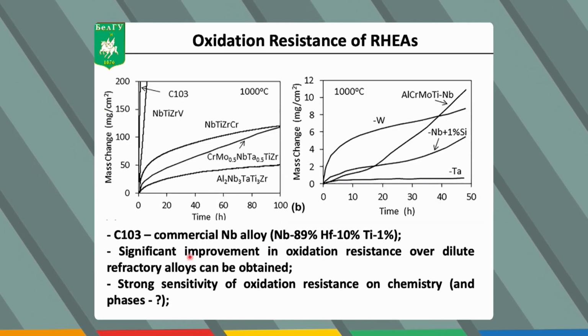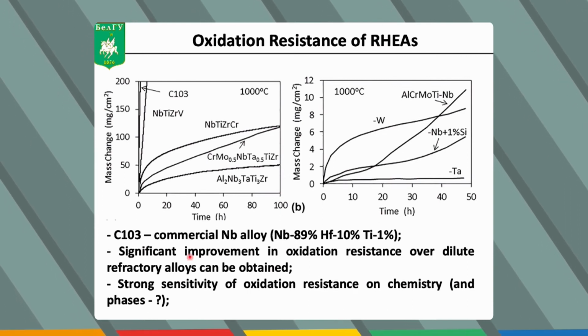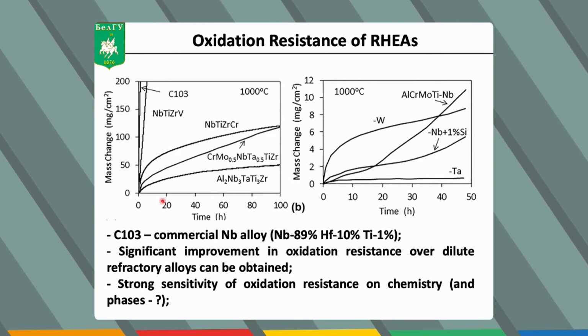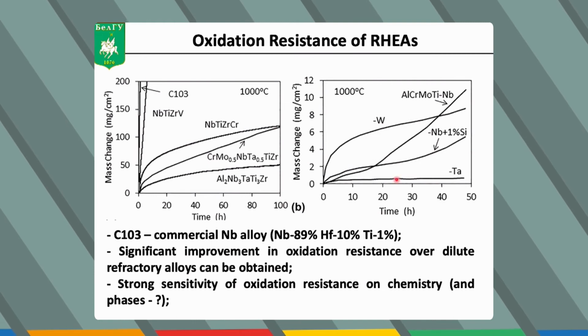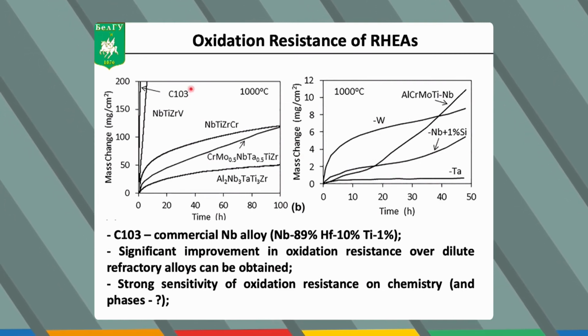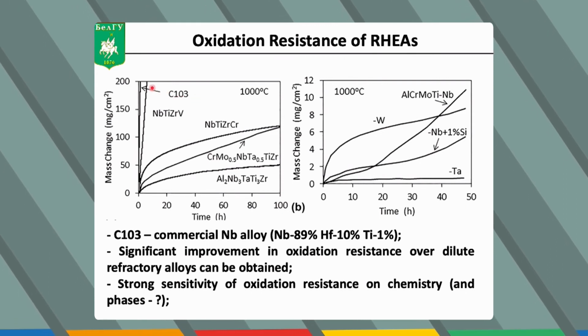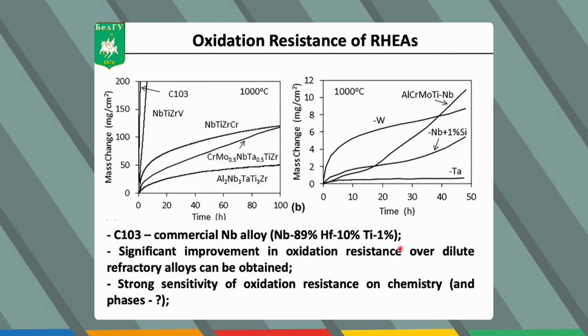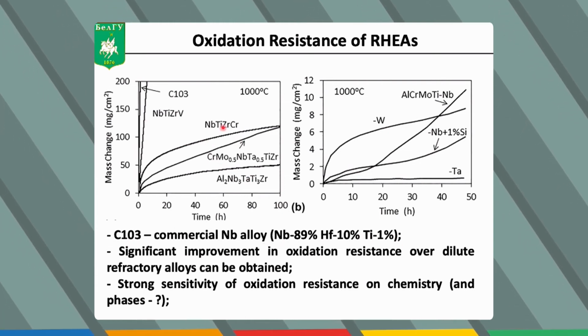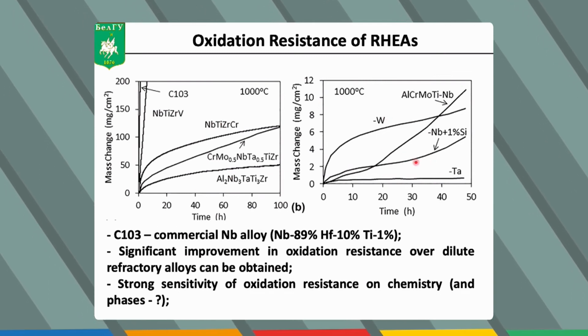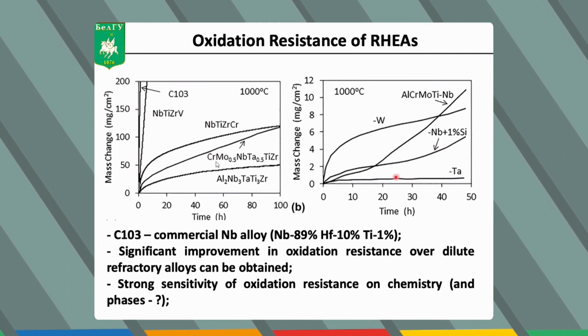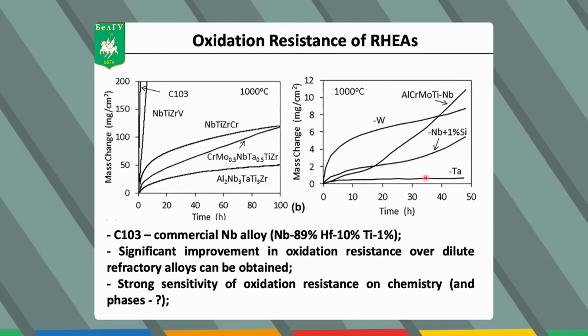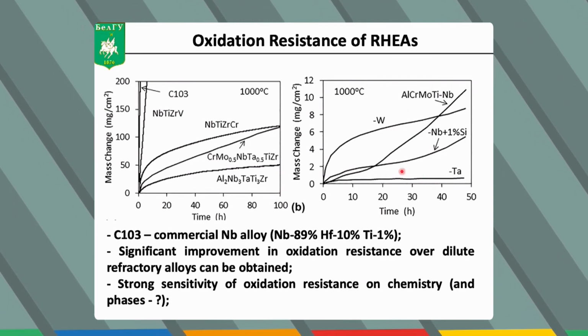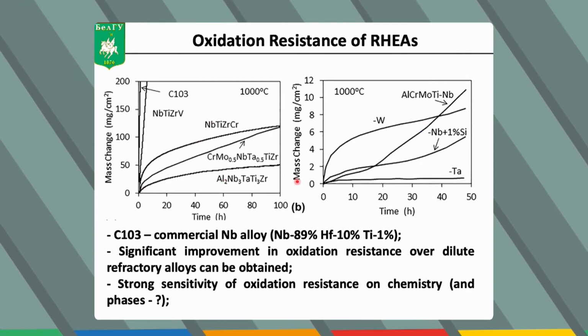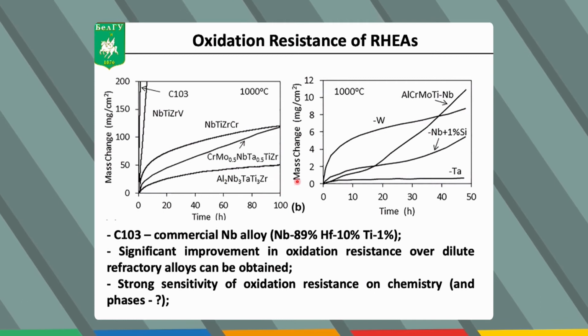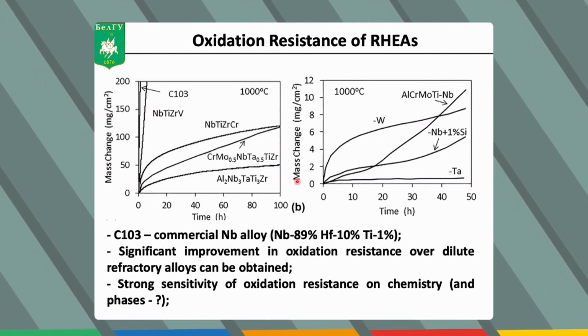And another very important issue for the high temperature materials is the oxidation resistance. And here I'm showing you some mass gain curves for different refractory high entropy alloys at 1000 degrees C. And here the C103 alloy, this curve, is actually the commercial niobium-based alloy. And you can see that all the high entropy alloys are performing better than this commercial alloy. And some of the alloys demonstrate very nice oxidation resistance. But still, there is a huge scatter in oxidation resistance between different high entropy alloys. Apparently, this is the effect of the elemental composition and most probably also the effect of phase composition.